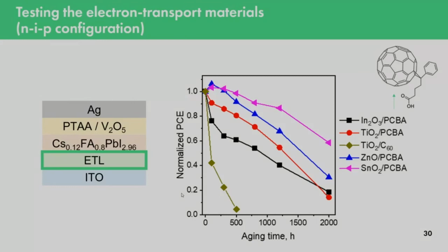You don't see any data for pure perovskites on this graph, because this kind of materials led to the complete destruction of the solar cell in just several minutes. So it was impossible to include them in this graph. But among these materials, the best was tin oxide with PCBA introduced between it and perovskite. So we can assume that PCBA works the same as PTAA in the previous experiment. It's like a barrier between aggressive oxide and perovskite material.